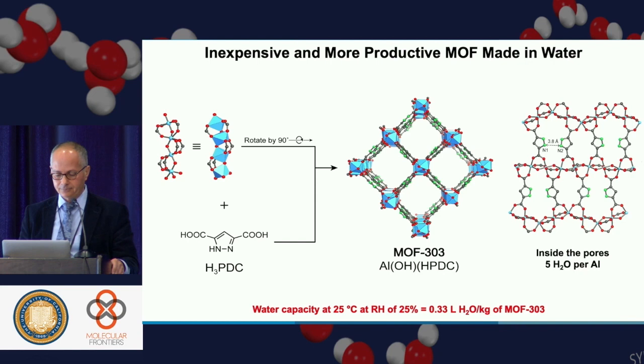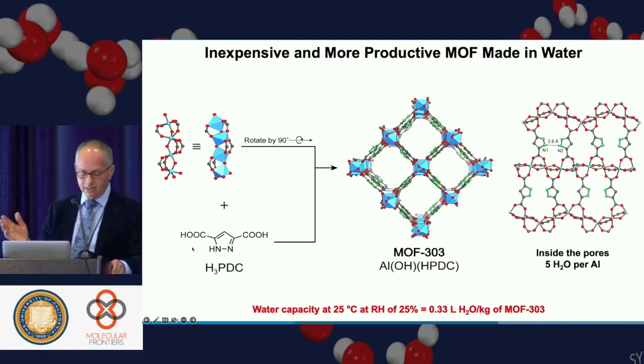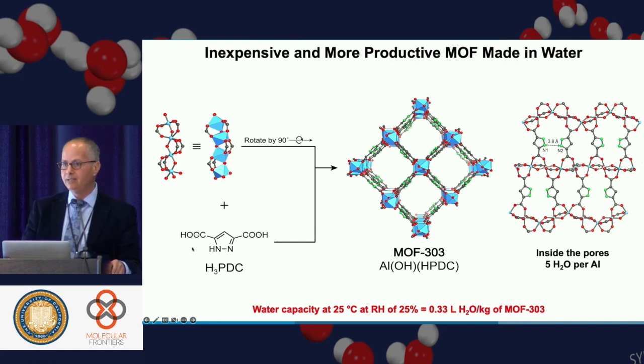and no hydrocarbons or other things that may be in the air. And this is another advantage of reticular chemistry: the MOF that I just showed you is a zirconium MOF. Now we can make an aluminum MOF and avoid the expense of zirconium. Aluminum is dirt cheap. And we have a linker like this. It's not widely available, but that's because there's no demand for it. We are the only demand for this material. And you make a MOF.